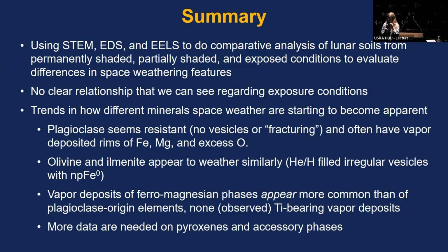And so whenever I see very thin coatings, that in my mind says that could be more sputtering, and also that those materials would be more mono or polyelemental, so not just one specific phase. If an impact hit a grain or a collection of grains, you'd expect to see a lot of different kinds, like a mixture of elements. But the fact that we're seeing pairs of elements gives me a sense of the scale at which these materials are being moved from one grain to another. So I don't have a good criterion, but thickness is what I'm going with at this point. Great, thank you.